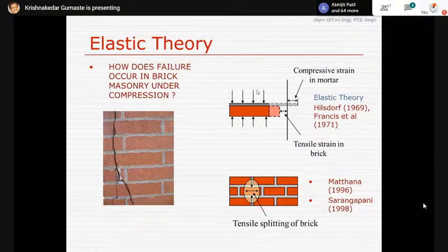In such cases, when it is actually loaded, what happens? The mortar tries to expand much more than the brick because of the variation in the elastic modulus. However, I expect that the masonry behaves as one, and thereby an equilibrium needs to be achieved. This means that the mortar needs to be undergoing a compressive strain, and the brick, on the contrary, has to get into a tensile strain.